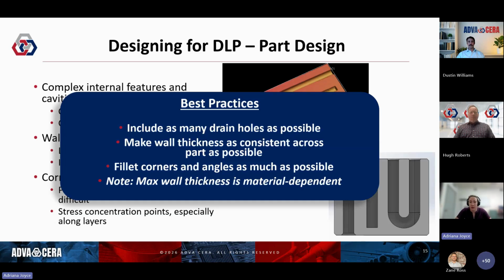What we like to do is include drain holes on closed features. So on that blind hole, we would put a smaller drain hole than the main one so that we could flow the slurry through and clean it out really well. For the wall thickness, if we can make the wall thickness as consistent across the part as possible, so no very thin sections connected to very thick sections, our burn off during the polymer decomposition is a lot more consistent, which makes it less likely for stress to build up in any particular portion of the part. We can also fillet the corners and angles as much as possible. So the smoother and rounder features that we can make, the less stress concentration we get, and the better the final part comes out. That max wall thickness is material dependent because it depends on the resin system and the ceramic loading content. So that one we have to work through on a part dependent basis, but it's very easy to talk through that and make adjustments to parts if we know what the critical features are at the beginning before we ever start printing the part.